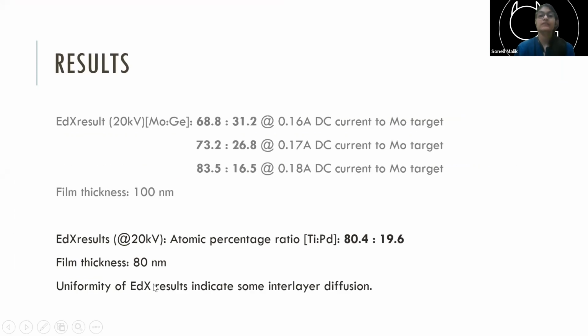So yes, I got the results here, and you need to fix a lot of parameters. At one particular parameter of DC current for my molybdenum target, I got roughly the concentration of 75:25, which I expected should give me a transition temperature for MoGe of around 5 Kelvin, and I kept the film thickness at 100 nanometers. For titanium and palladium also, similarly, I got the concentrations that I wanted.